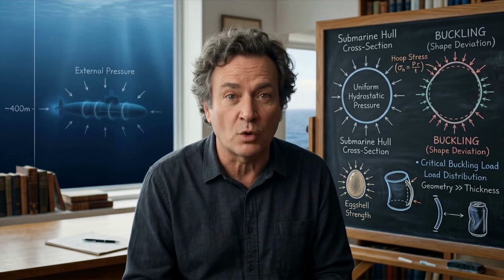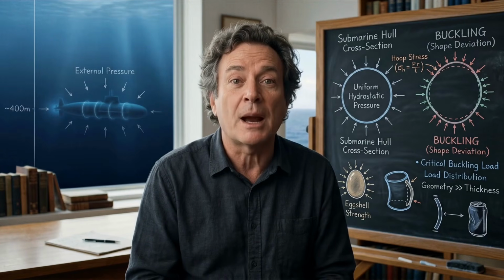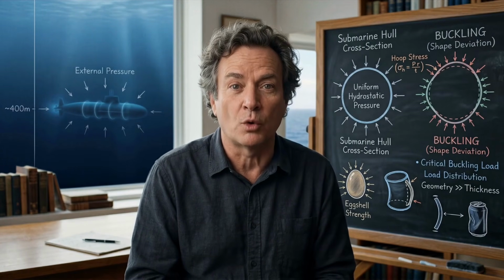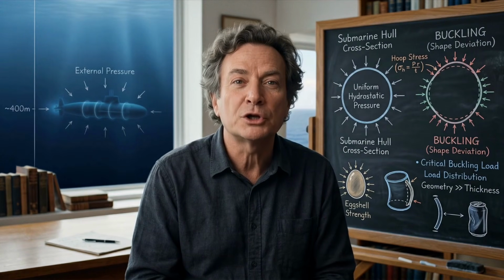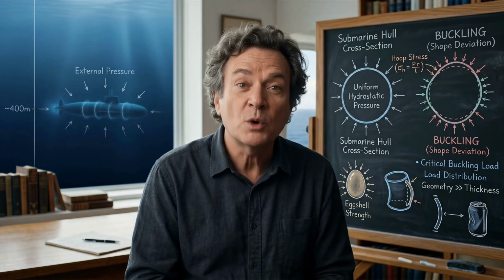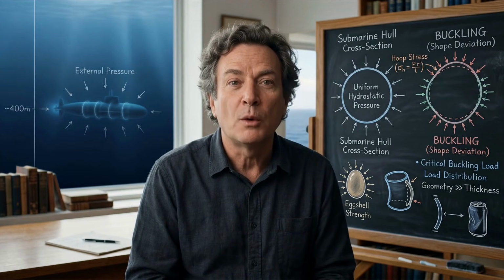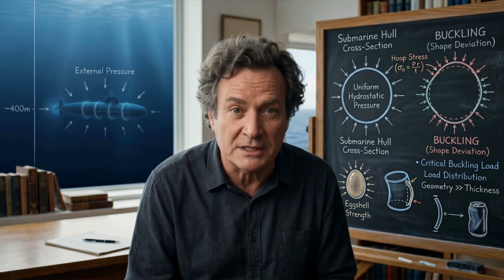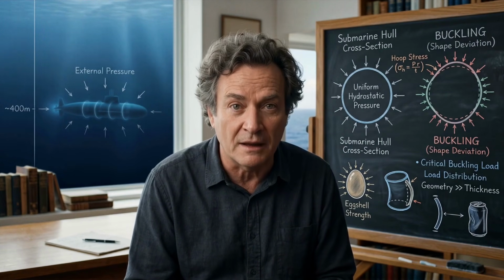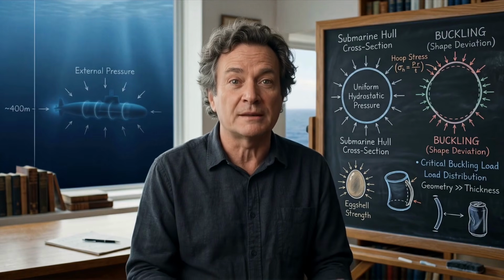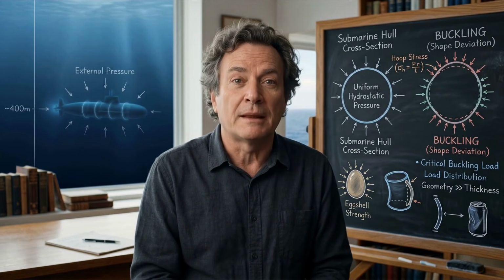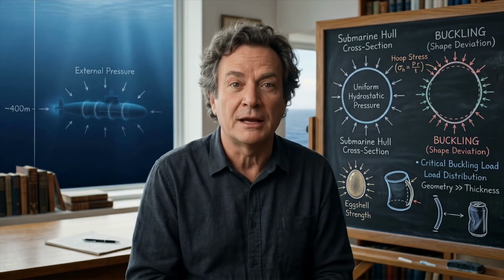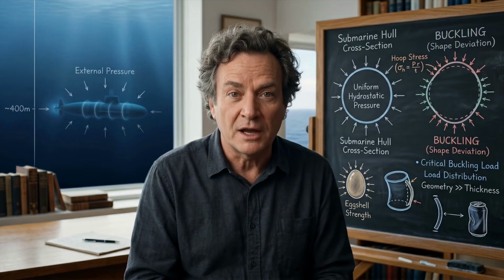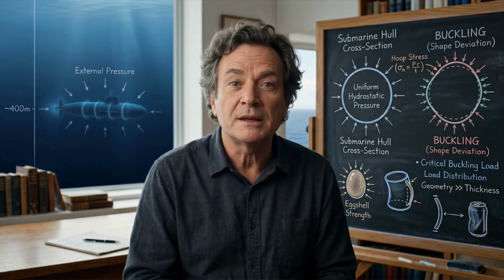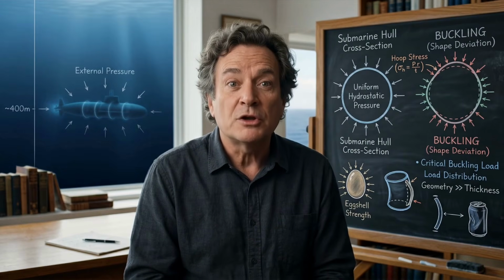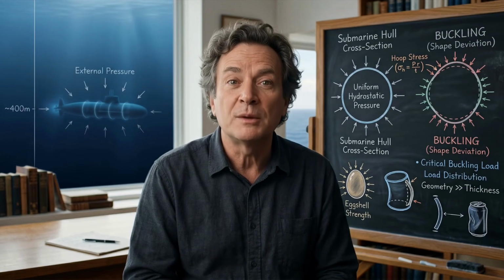This is, in a strange way, the deepest thing I want to say about why submarines do not implode. They do not implode because they are not rigid. They are not brittle. They are elastic, they deform under pressure, and then they return to their original shape when the pressure is released. Exactly the way a spring does, exactly the way any elastic material does, provided the stress remains below yield. The submarine's survival is not about being immovable. It is about being precisely, correctly, controllably movable, flexible enough to deform, stiff enough to return, shaped in such a way that the deformation is distributed so uniformly that no single point is ever pushed past the yield limit.